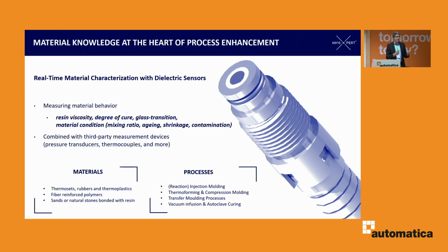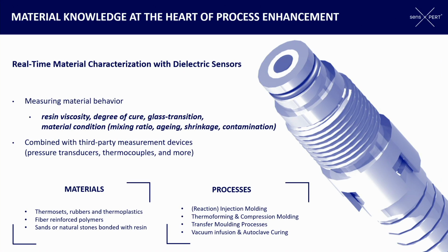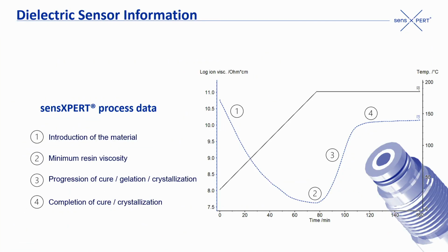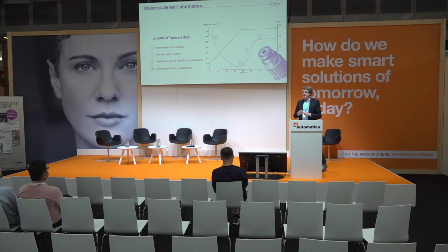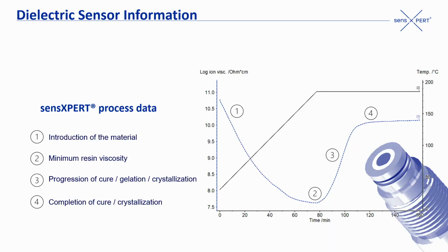And from this information, we can then infer various material properties and also quality indicators, such as the viscosity of the material, degree of cure, TG, and also, for example, influences on the material, such as aging. I'll give you a few examples also later on. What we basically see is a dielectric response. So this is indicated by this blue dashed line here.